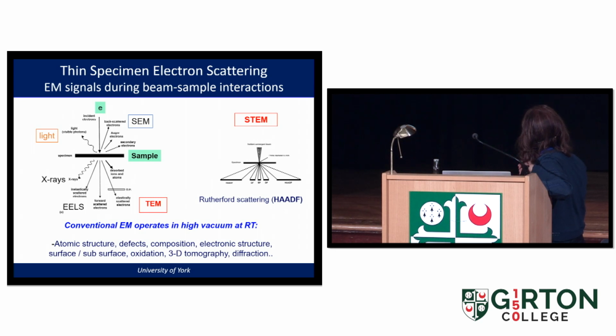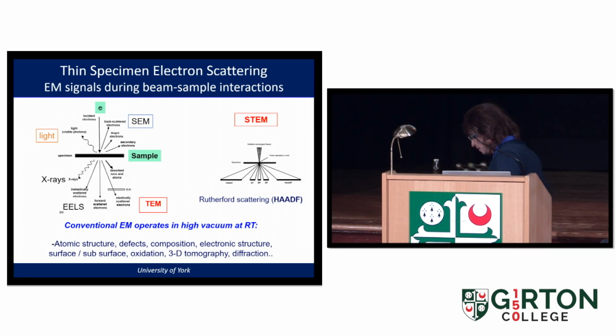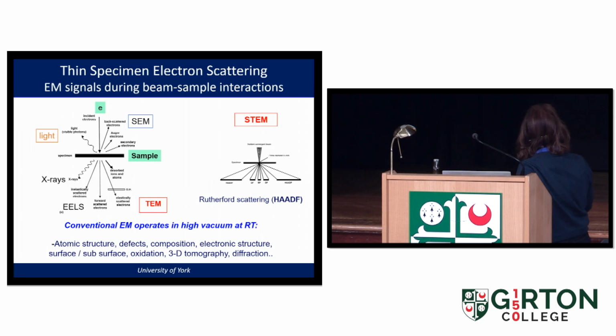And during this interaction, we also get X-rays, and they are characteristic of the elements in the species. For example, it can tell us what these atoms are, whether they are sodium or chlorine or copper or whatever. So the combination of that is very important to have both structure and composition. And we can also scan a probe of electrons onto the sample, like that scanning, and collect these highly scattered electrons. In this case, the intensity is approximately proportional to the square of the atomic number or proton number. So for example, if you have platinum on carbon, if you square it, you can see platinum is going to look very bright. I'm going to give you some examples later on.